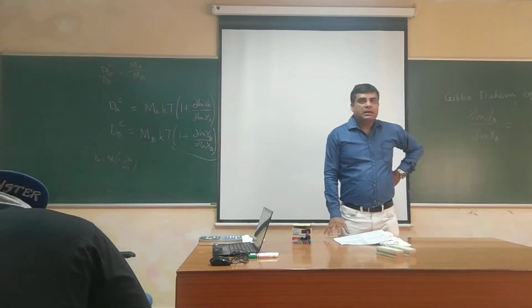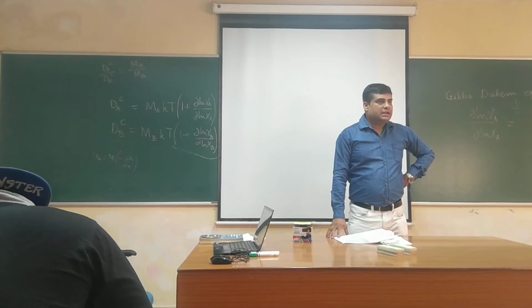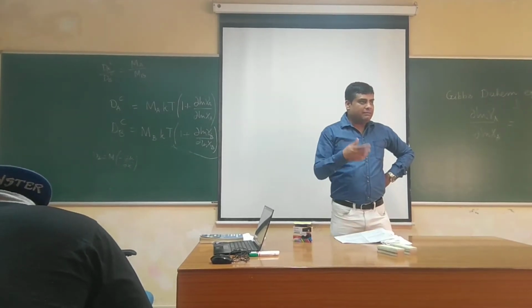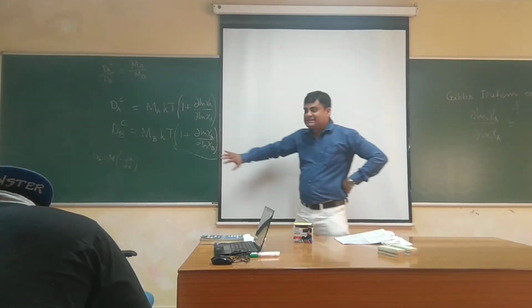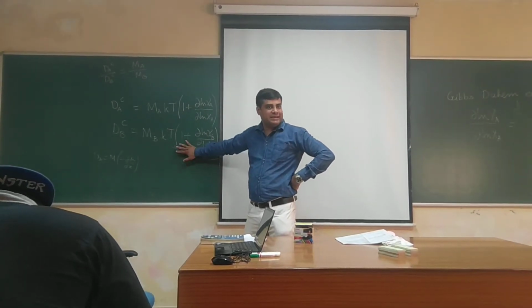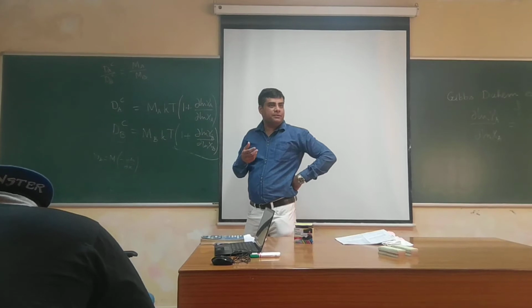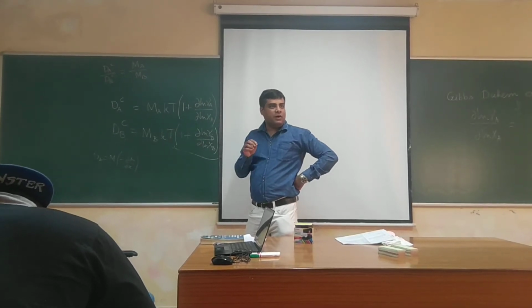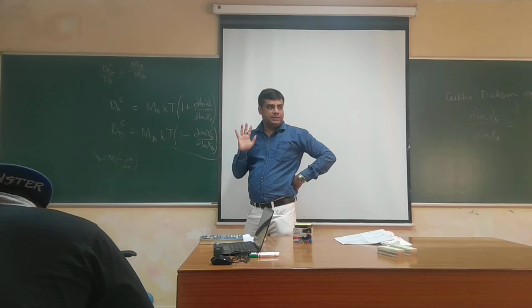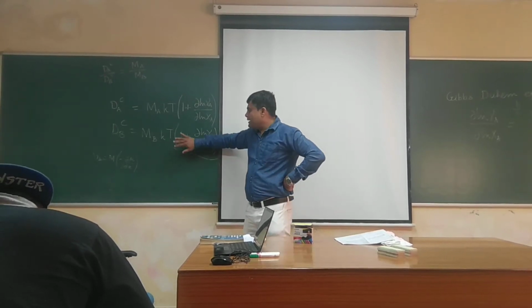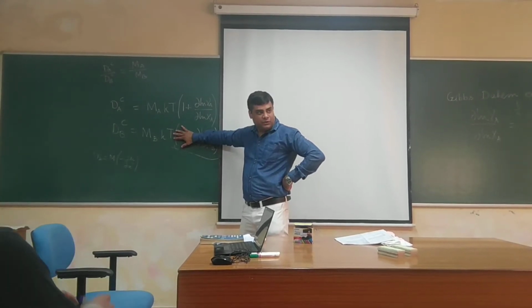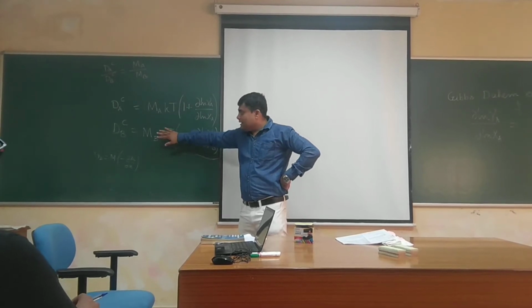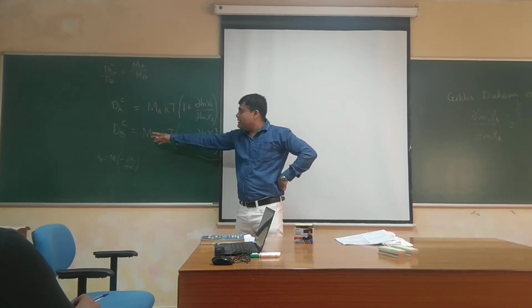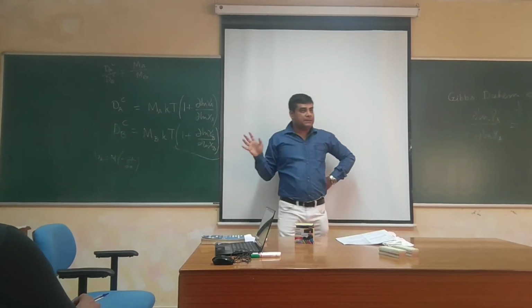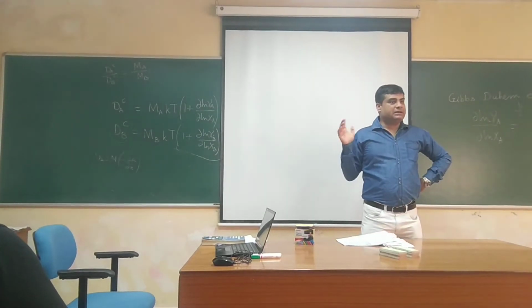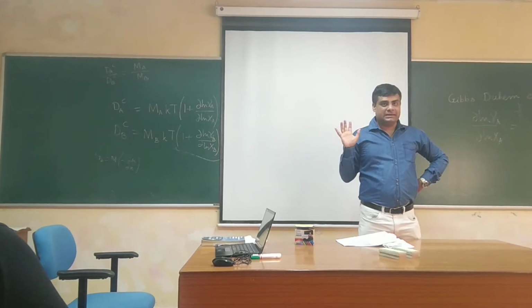the value of which actually comes into picture. It acts as a weight, W-E-I-G-H-T, weight in the diffusion of atom over and above the random jump. If there were random jump only, which happens only in ideal solution, the intrinsic diffusion coefficient will be given by MkT, multiplied by the thermodynamic factor to take care of the non-ideality.